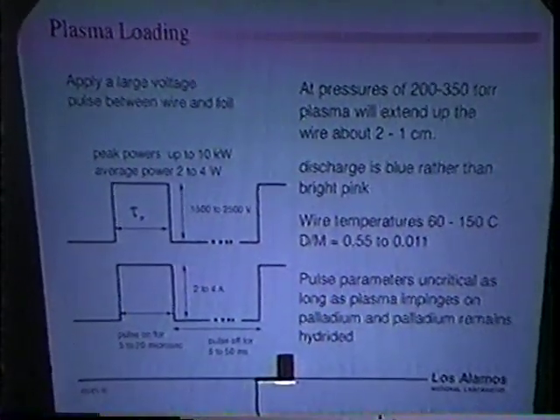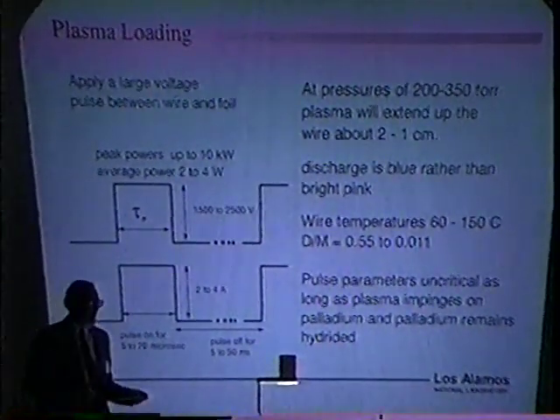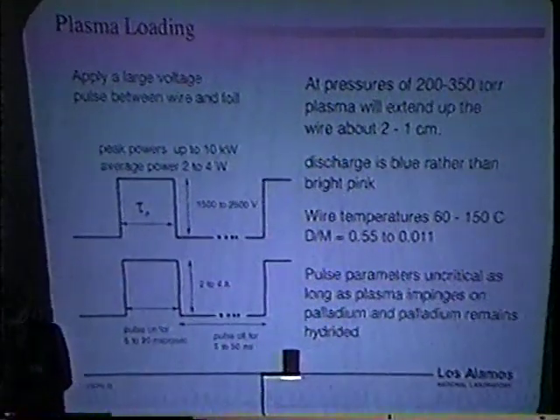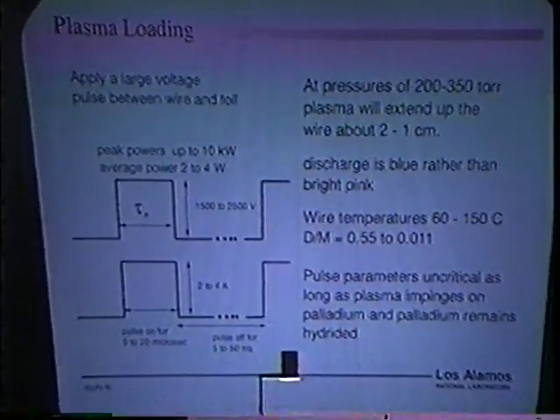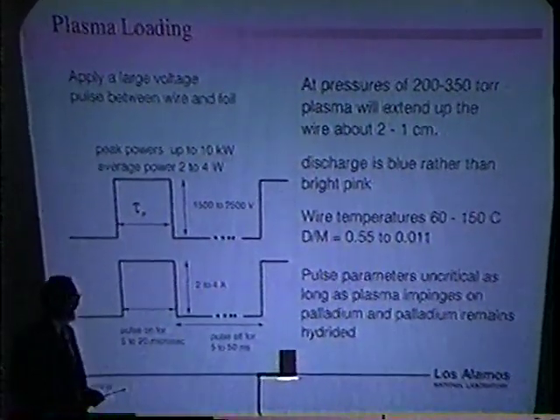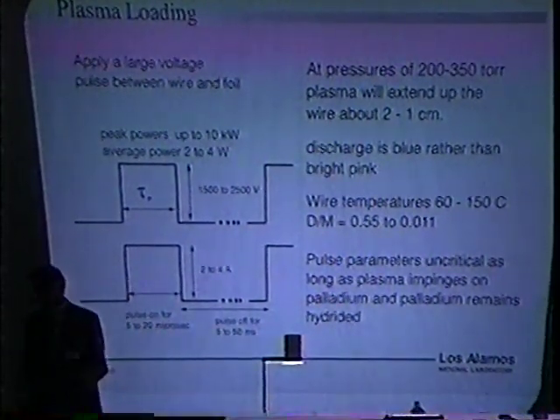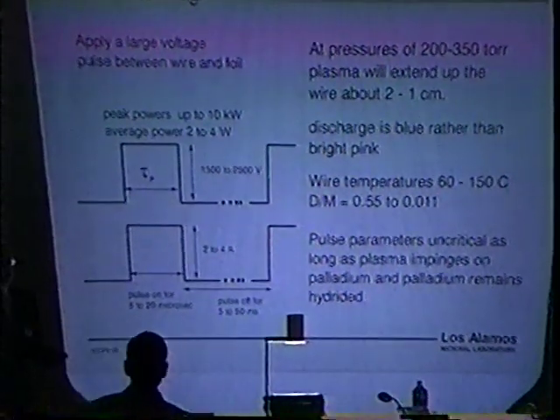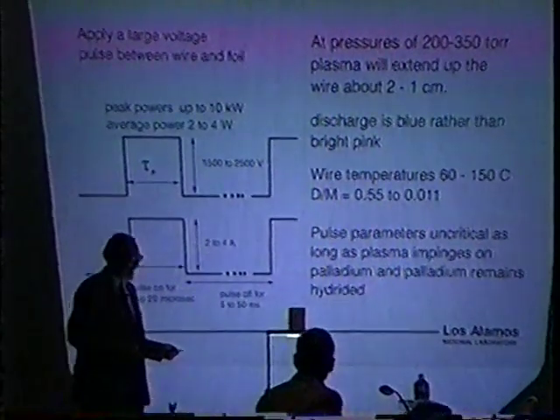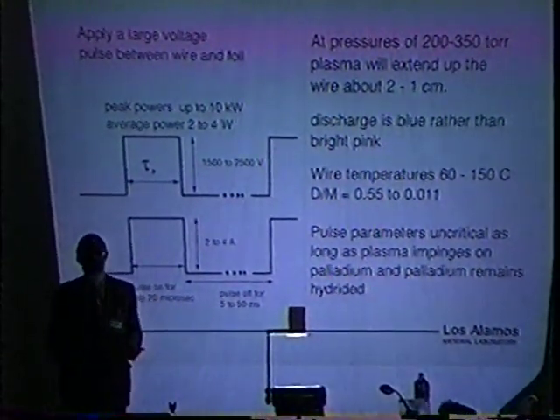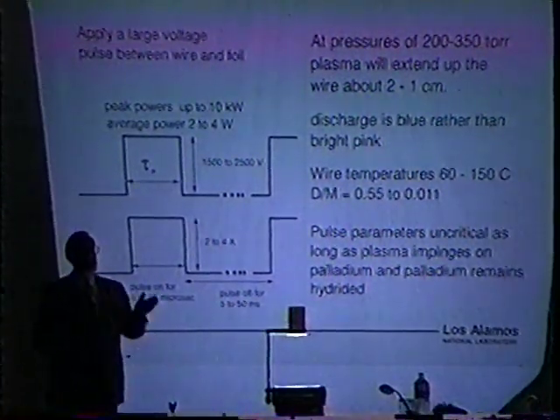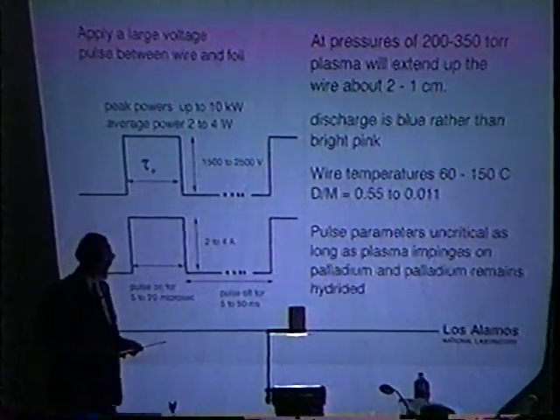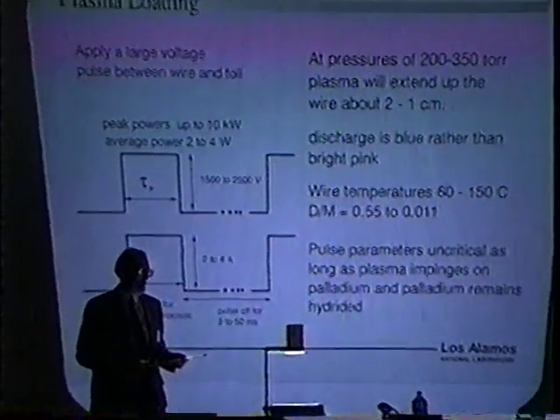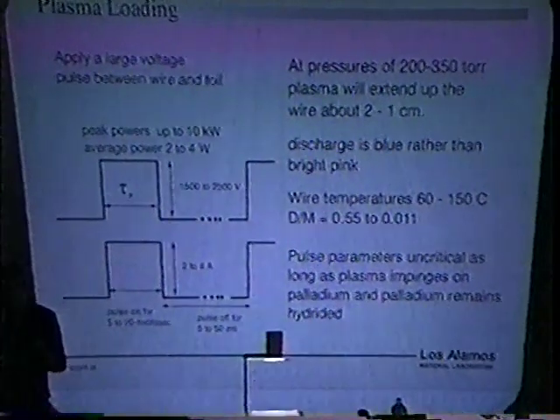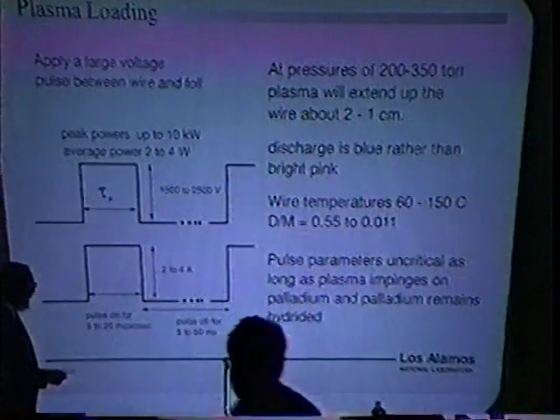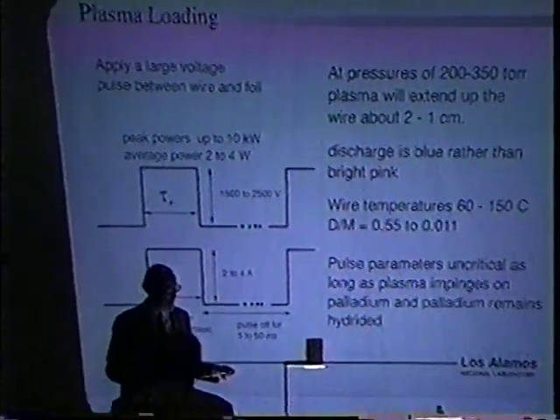He found recently, somewhat unexpectedly, that the discharge is not what loads the palladium. The palladium must load prior to the discharge by gas loading. And that's very sensitive to the nature of the palladium as well as the nature of the gas. And he's found now that many of the samples that were looked at in the past that did not work probably did not work because they did not load. He now has a method to test the gas's ability to load, and so he can do essentially like a canary in a mine, check the gas to make sure that it's suitable, by loading another piece of palladium where he can measure the resistance and see the loading characteristics. Once that problem was solved, things began to improve, but unfortunately he seems to have run out of time.